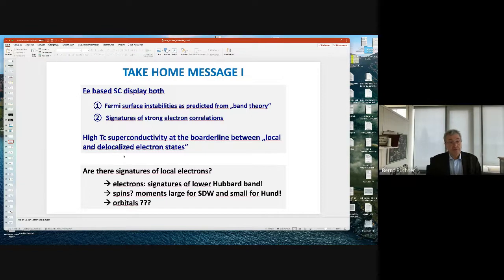Now, the next question which arises from that is, are there signatures of local electrons? I showed you the signatures of the lower Hubbard band from photoemission. What about spins? Of course, we have this spin density wave, and it turns out that the moments which you find there are larger than what you get from simple band structure calculations or what you expect for a simple spin density wave. So this already points to the fact that probably some local degrees of freedom play a role as well.